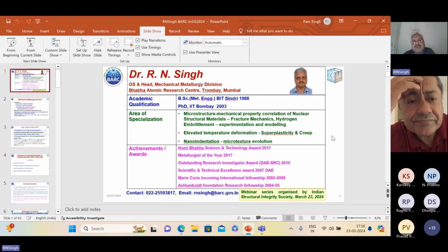Near the crack tip, because it is elastoplastic material, hydrogen accumulation has not taken place. It is still as-received material. So when this ligament near the crack tip is unable to support the load, at that time it snaps. The bright region we are seeing is because of the ductile snapping of the ductile matrix, and the darker region is because of the cleavage failure of the hydride. So the entire process repeats in a discontinuous manner. That's why it is called delayed hydride cracking. I hope I am able to answer your question.